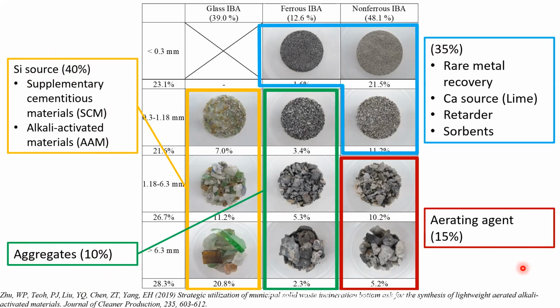The smaller particles are more problematic because of the high trace element, the heavy metals. However, with this 35%, we can consider rare metal recovery, and it's also very rich in calcium, so potentially it could be used as a calcium source replacement. This also shows the retarding effect, and the smaller particles with high surface area could be considered for use as sorbents.